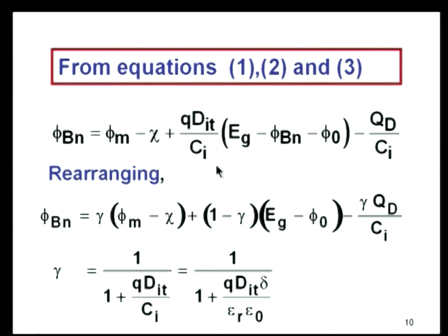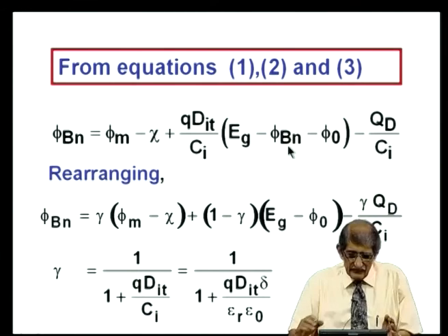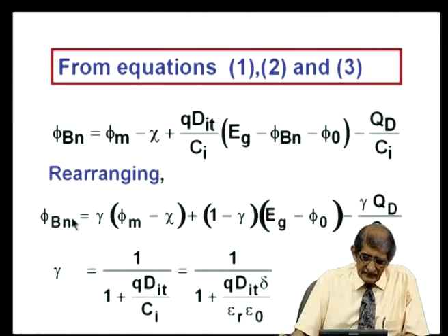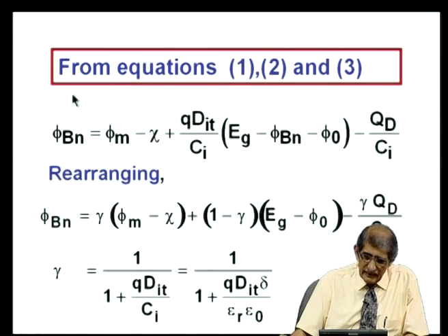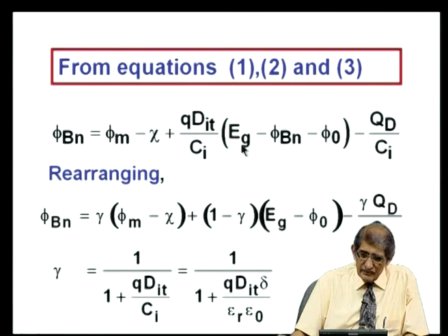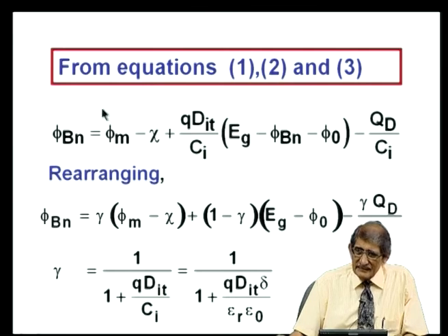Now, I will not go through that thing. You can actually work it out yourselves, rearranging the whole thing. You can see there is phi b n here, phi b n here. Take them to the left hand side and right side. I can write it as phi b n onto that side. You will have phi b n into 1 plus q D i t by c I going to the left hand side. So, you will have phi b n is equal to gamma times phi m minus chi, where gamma is actually 1 by 1 plus q D i t by that. So, that is by rearranging that.